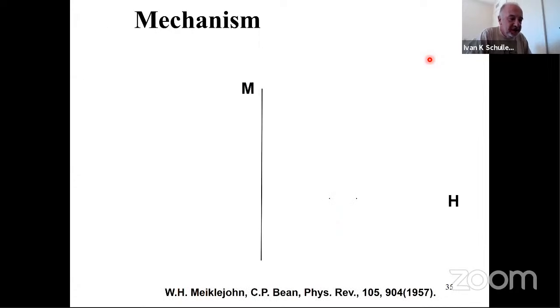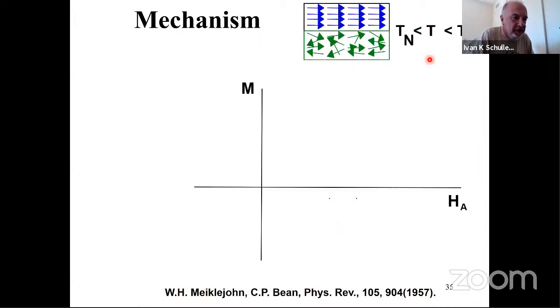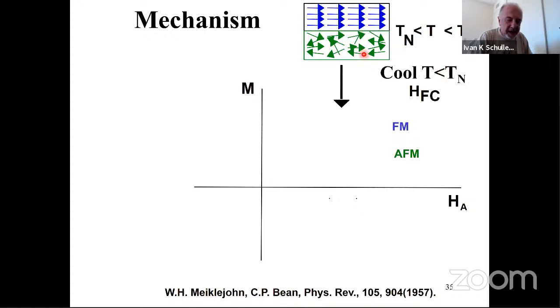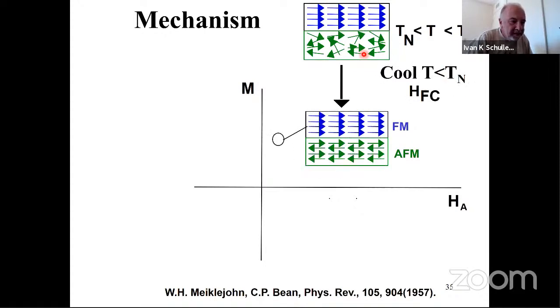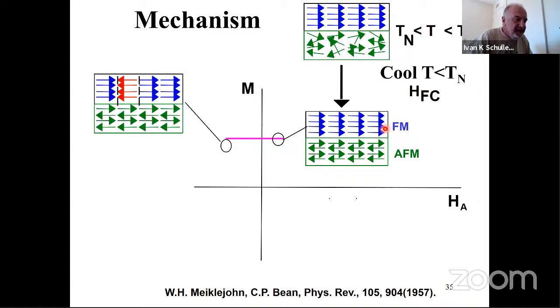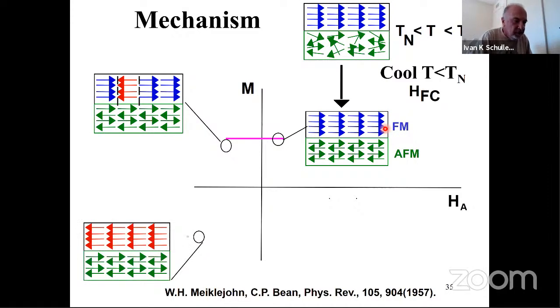So here it is, the mechanism that you would expect. The mechanism that you expect, as Meiklejohn and Bean explained to us, is you take a ferromagnet, which points towards the right, and at some temperature, which is below the Curie temperature of the ferromagnet, you cool it in a magnetic field, and you cool it below the Néel temperature of the antiferromagnet. The antiferromagnet orders, and because of that interface there, the antiferromagnet applies an internal field on the ferromagnet. Because of this, the hysteresis loop shifts towards the left. It's like adding an extra field. So the field is really not zero, it's something else. And so the hysteresis loop is shifted towards the left.